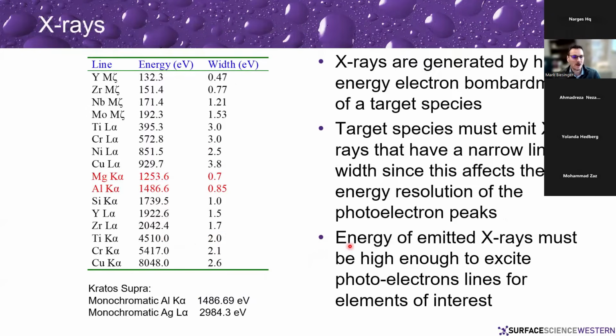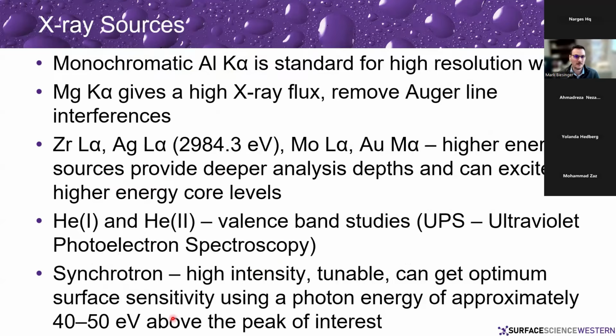Some of the X-rays that are commonly used for XPS, the most common is aluminum K alpha X-rays. Probably the next most common, but you don't see it much anymore, is the magnesium source. We're seeing a lot of work now using higher energy X-rays to go deeper into the sample. For example, our Kratos Supra also has a silver L alpha source at 2,984 eV. Yeah, and again, those are the standard X-rays.